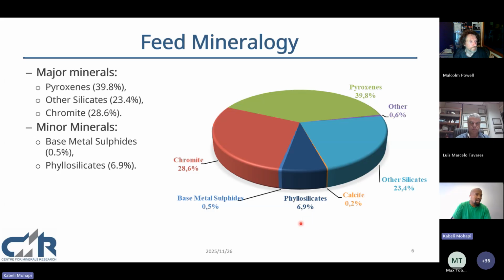To talk first about the feed mineralogy, or rather the feed characterization. This graph shows a pie chart which was created using the bulk mineralogy characterization that we performed on our feed. In it, we have a significantly high proportion of pyroxenes and other silicates, accounting for over 60% of the sample. We have almost 29% of chromite, which is slightly lower than typical UG2 tailings, owing to the fact that there are chromite recovery plants fitted along the value chain of the ore that we received.